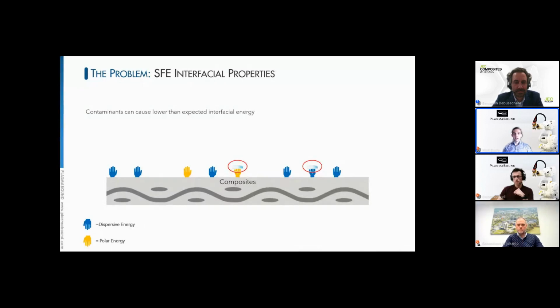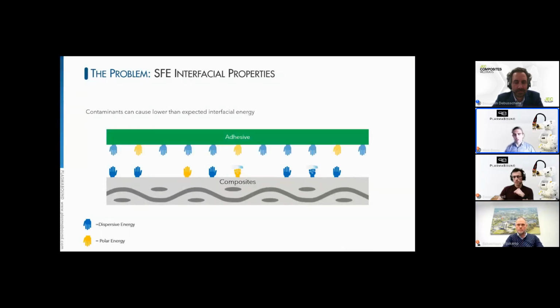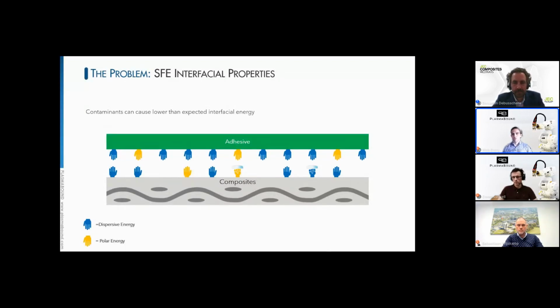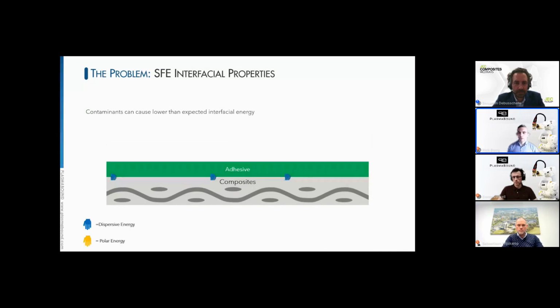So if we take the adhesive and do the exact same kind of metaphorical structure, and look at its surface tension when it comes to a liquid or a pseudo liquid, it could be represented as such. With many more hands, and that's important to point out, adhesives usually are quite energetic to form an agreeable bond. So we've done no pre-treatment to this surface. It is just a standard FRP surface. When the adhesive comes in contact with it, unfortunately, we've only 3 forms of agreement across the surface. So we end up with a poor bond.